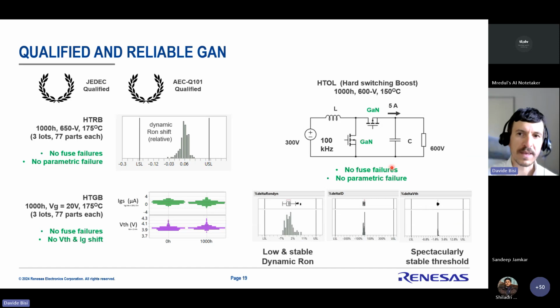Of course, if you want to go into applications, reliability is key. And so we have made extensive qualifications and reliability campaigns. So our products are JEDEC qualified and automotive qualified. And key results here, you can see the high temperature reverse bias, 1,000 hours, 650 volt at 175 C. We need to do 3 lots, 77 parts each, and have no failures to pass. And so you can see here we had no failures, and you can see the dynamic Rds(on) shifts are really small after the stress, so really strong and robust technology.